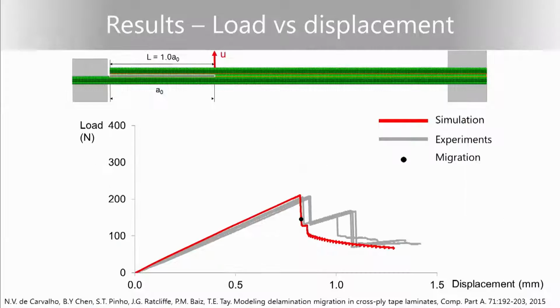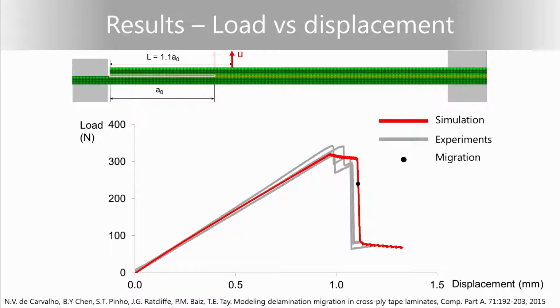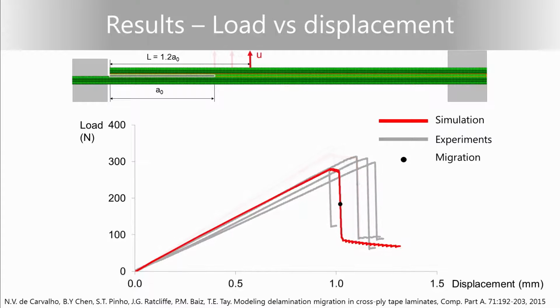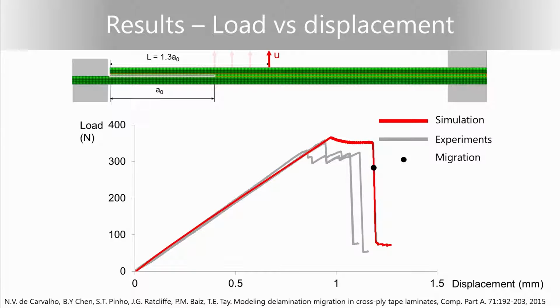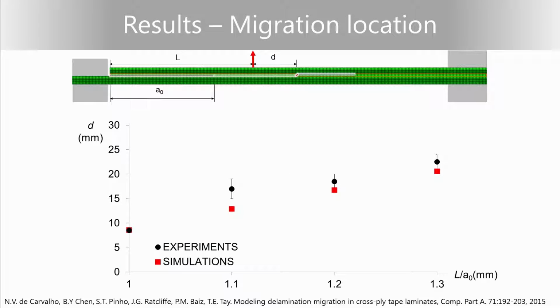So if you look at the first case they've done, you can see the load displacement curves on the screen. The experiments are in gray and the simulation in red. If we change the application of the load, we get very similar load displacement curves, and in all cases, we get quite a good prediction of the maximum load. If we look at the position of the migration, here I'm plotting in the horizontal axis the 4 different cases that they've tested.